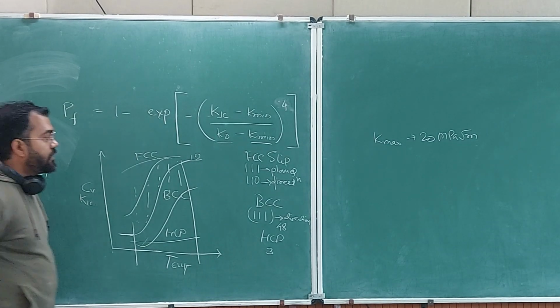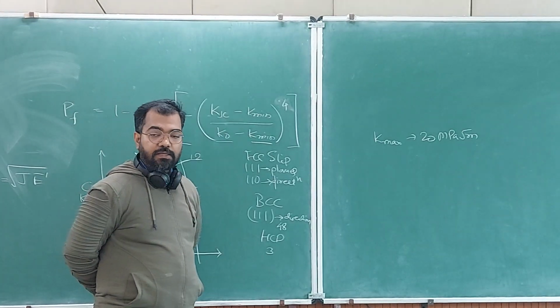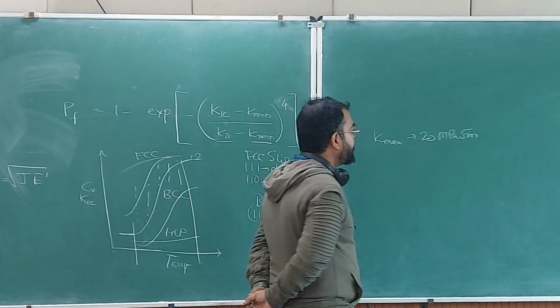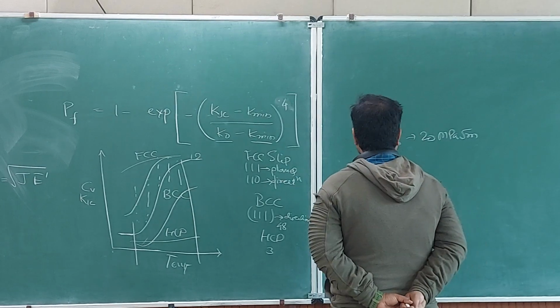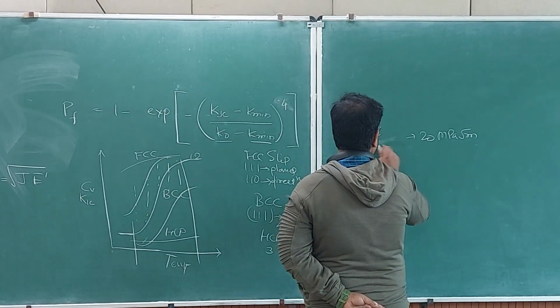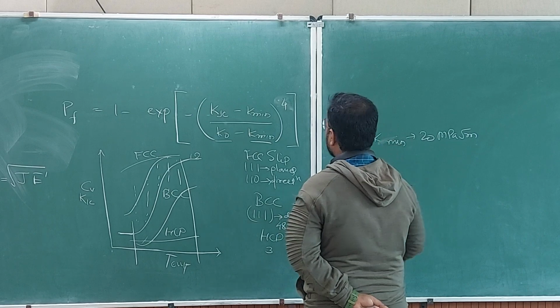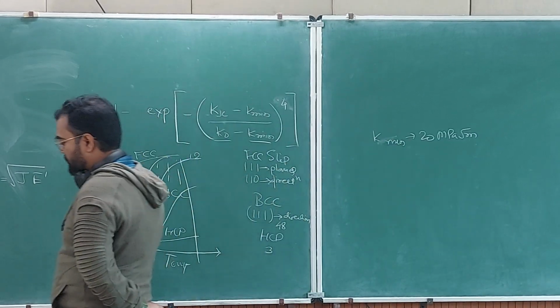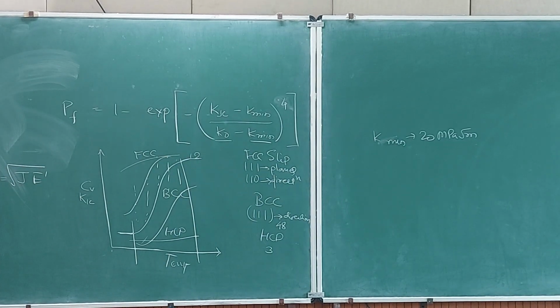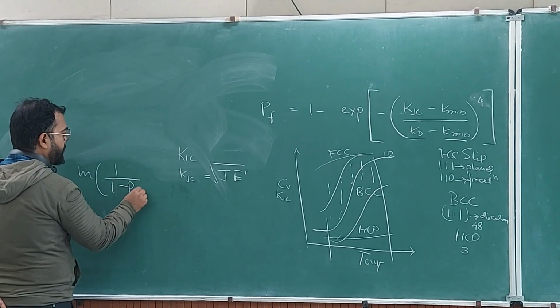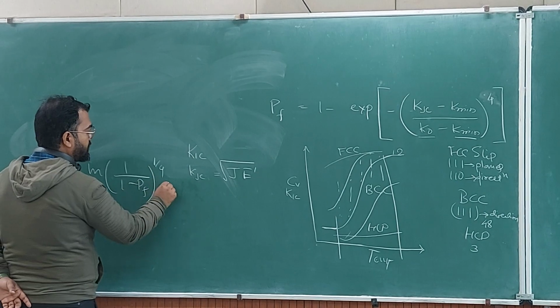Okay, and also in upper shelf you don't have much scatter. The scatter is mostly in the ductile to brittle transition. So then K minimum becomes 20 MPa root meter, and now the problem is, what is K naught? K naught is a reference parameter that you can find out. So then you have to put KJC is equal to K naught. Okay, so then ln of 1 by 1 minus PF to the power 1 by 4 will become